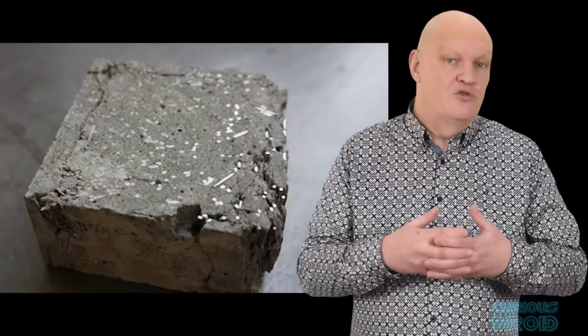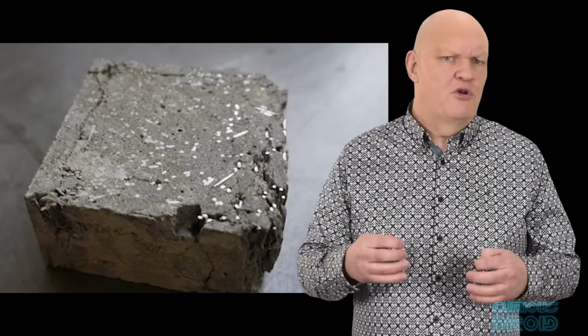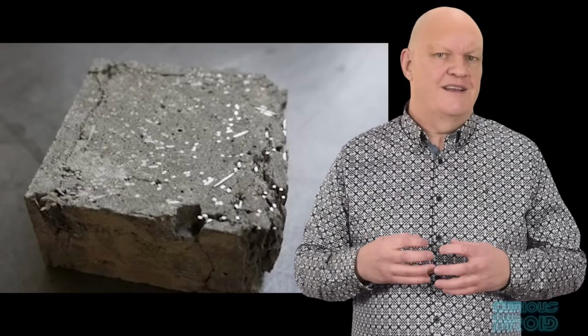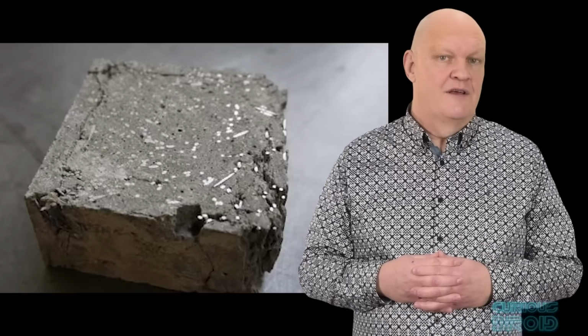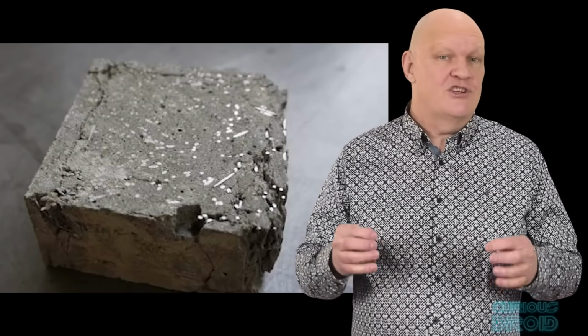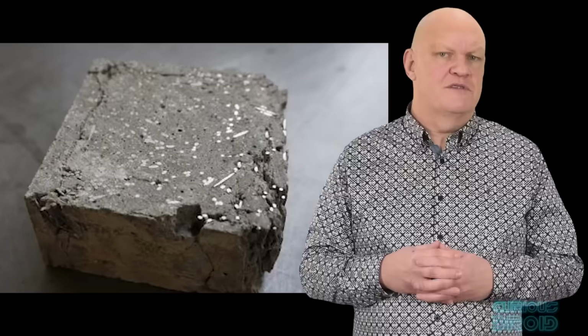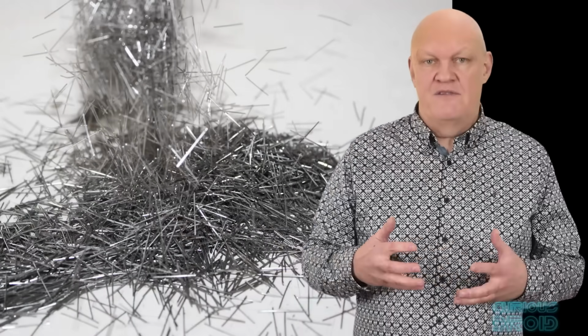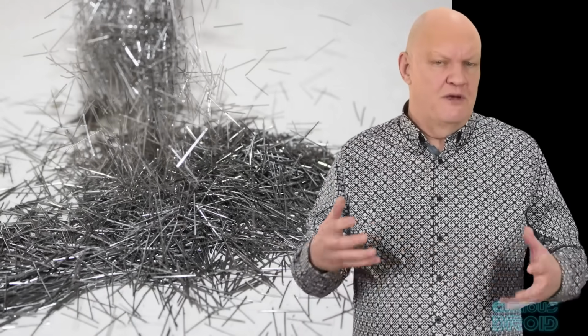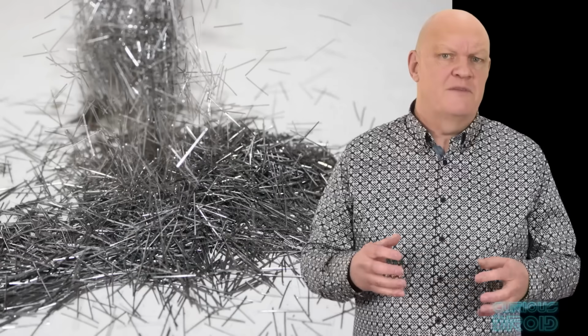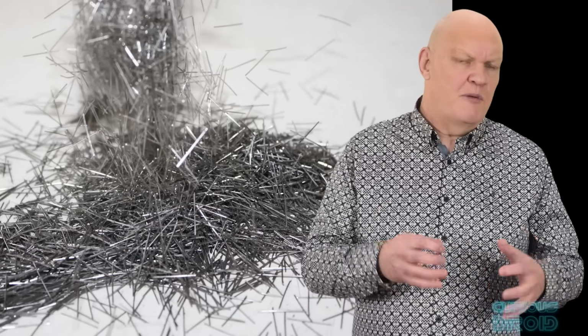UHPC uses normal cement, but much purer quartz flour and fine sand, plus other additives, but also includes an addition of up to 1% of fibres of high-carbon steel, PVA, glass, carbon, or a mixture of all of them. These fibres help stop cracks from propagating.